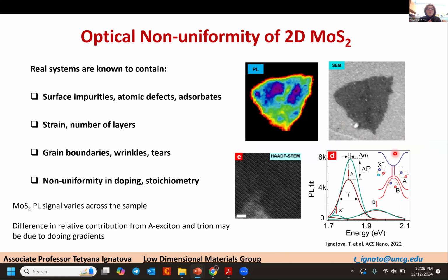Okay, optical non-uniformities of molybdenum disulfide exist immediately after you take the material from the furnace after growth. It is probably because of impurities, atomic defects, adsorbates, strain introduced from the substrate, number of layers and appearance of second, third layer formation, grain boundaries, wrinkles, tears. So many different reasons can cause non-uniformities of as-grown two-dimensional MoS2. And here you can see a photoluminescence map for a sample. This sample was actually covered on top with graphene, which doesn't matter for now, but you can see that the photoluminescence profile is not flat at all.